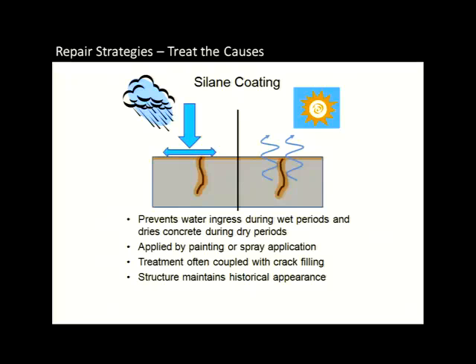Probably one of the most effective ways that we have for mitigating ASR, as I mentioned, is to dry the concrete out. There's a material called a silane. You may also see this as a siloxane. It's basically either a water or alcohol-based material that you literally paint or spray onto the exterior surface of the concrete. And it really acts like a one-way mirror. So it allows moisture to leave the structure, but it does not allow moisture to come back in.